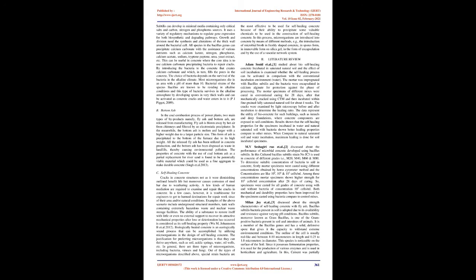The cracks were examined by light microscopy before and after incubation to determine the healing ratio. The data represent the utility of bioconcrete for such buildings, such as tunnels and deep foundations, where concrete components are exposed to soil conditions. Results showed that the self-healing properties for the specimens incubated in water and natural saturated soil with bacteria showed better healing properties compared to other mixes. When compared to natural saturated soil and water incubation, maximum healing is done for soil incubated specimens. M.V. Seshagiri Rao et al. discussed the performance of microbial concrete developed using Bacillus subtilis.